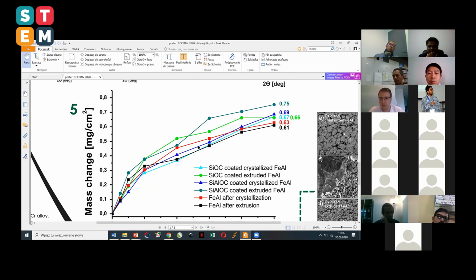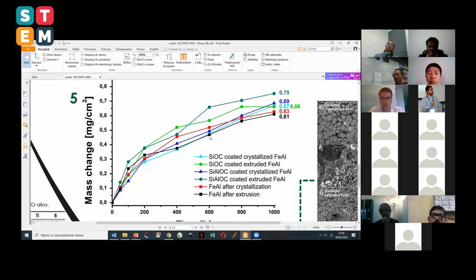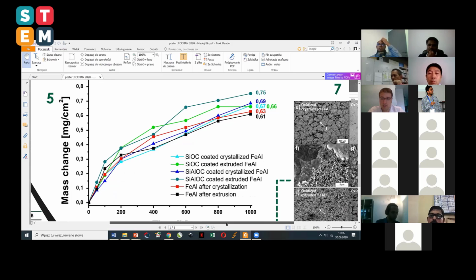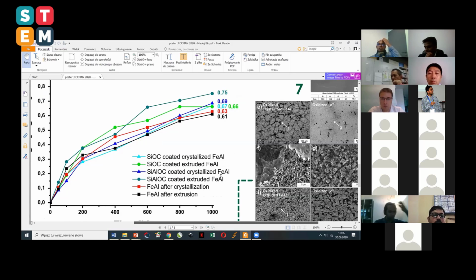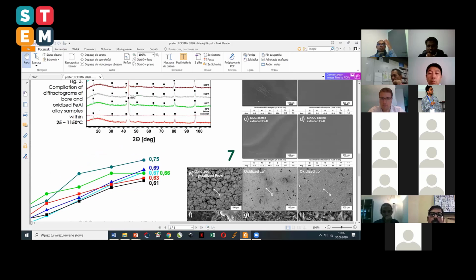oxidation of samples uncoated and coated with polymer-derived ceramics. And first of all, I would like to present to you the mass changes within 1000 hours. And the results may seem a little bit ambiguous at first glance because of the fact that the lowest mass changes, or the lowest mass gains, were observed for the uncoated material. So, as I said, it could be ambiguous at first glance, but let me show you further results.